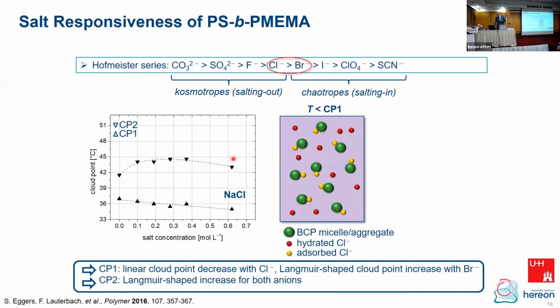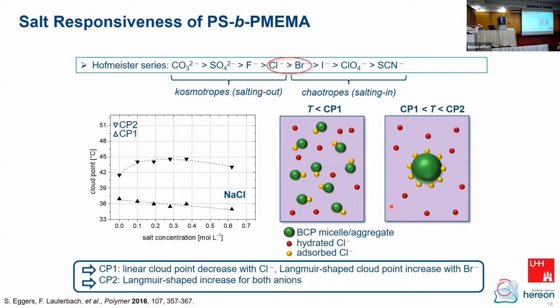And here's just a cartoon of how one can try to picture that. So you see here two sorts of chloride besides the green block of polymer micelles or aggregates. The red one is the hydrated chloride, and the yellow one is the chloride which is adsorbed to this micelle. And below cloud point 1, we have basically the chloride as free chloride, and just a few are maybe attached to the block copolymer micelle, but here between cloud point 1 and cloud point 2, we have a stronger adsorption of chlorides to this micelle, and that leads to this salting-in effect.